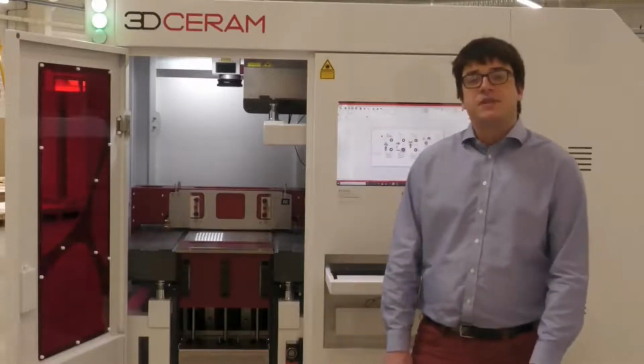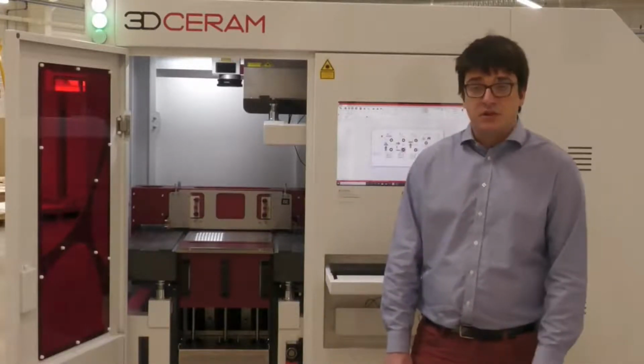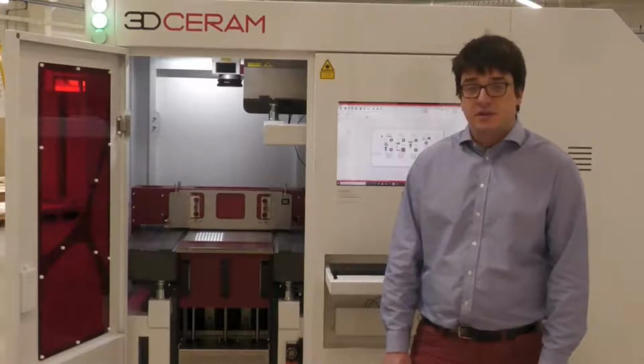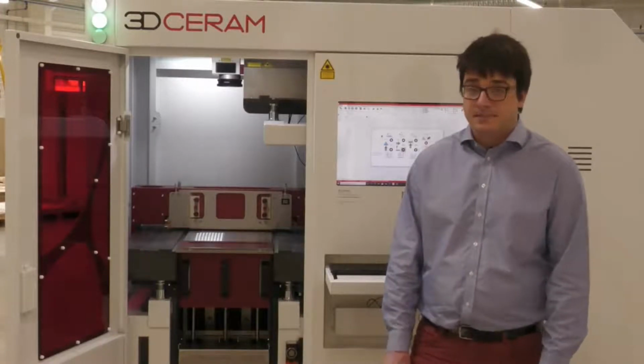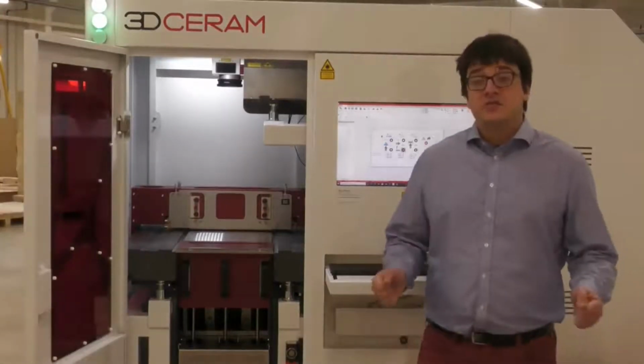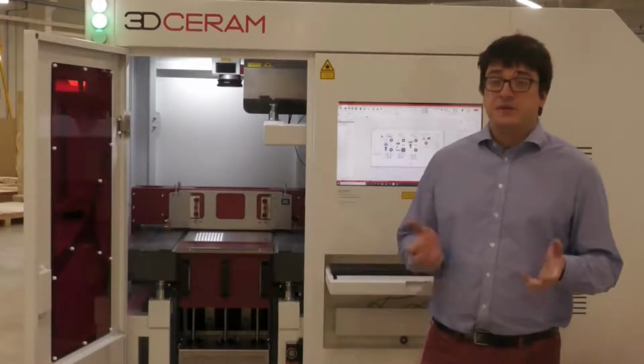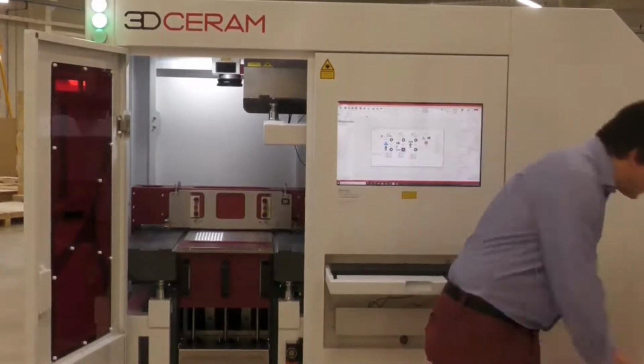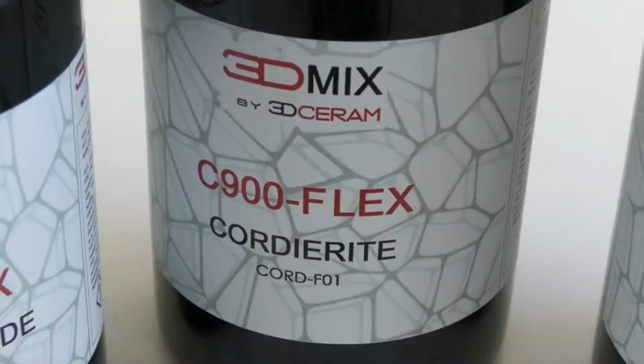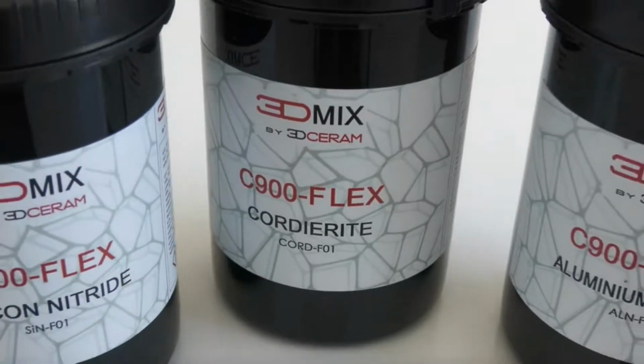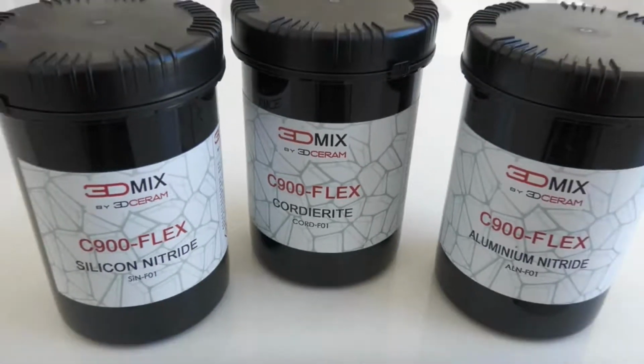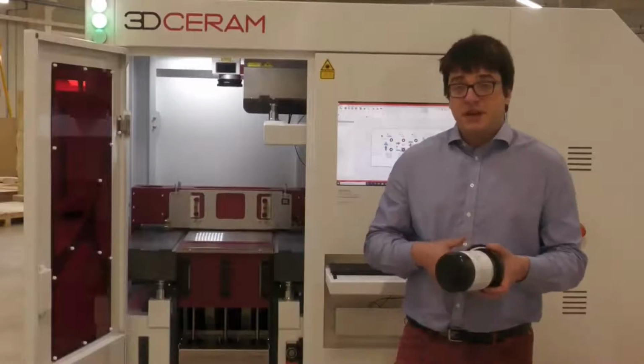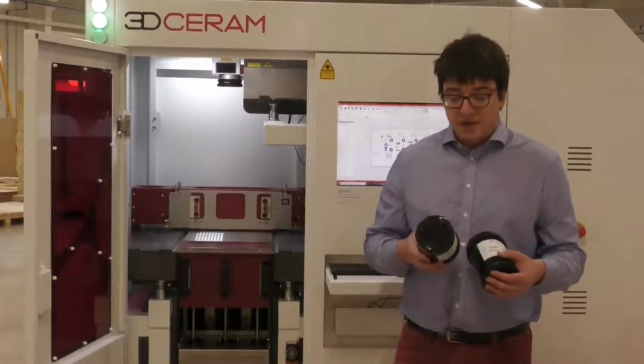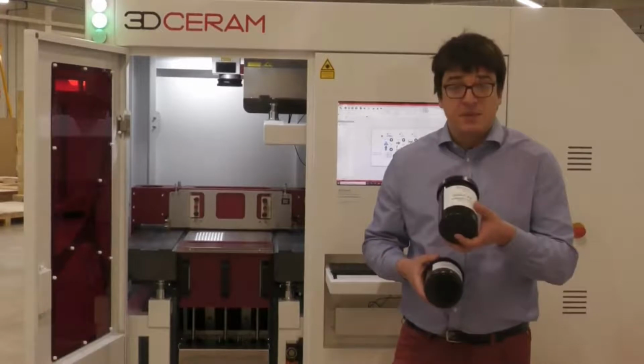This mix is printed from the bottom to the top, allowing you to print firing freestanding supports at the same time as the parts needed. Because the C900 Flex is our first printer, a lot of different materials have been developed by the 3D Ceram teams to work on this machine, such as cordierite, silicon nitride, aluminum nitride, zirconia, HIP, or TCP, for example. The skull implants printed by 3D Ceram for Joël Brie have been printed with HIP.